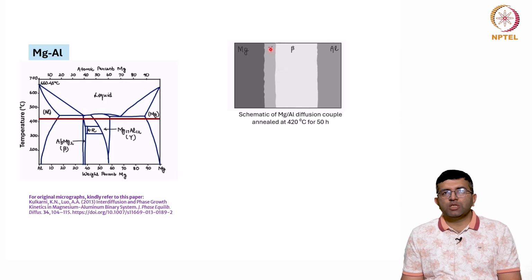So, here what you see is a gamma and a beta phase growing. Okay. So, gamma and beta. Again, you see here that although the beta is almost like a line compound in this region, the thickness to which it grows is much more than gamma. So, please do not confuse yourself thinking that here the gamma composition range is wide.